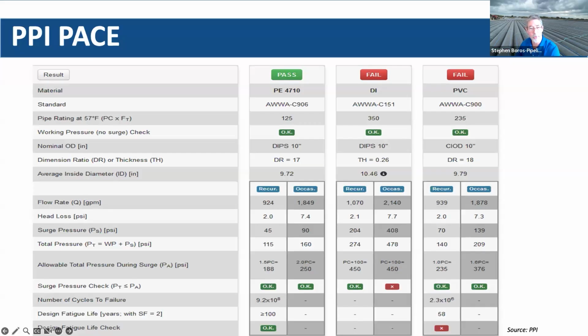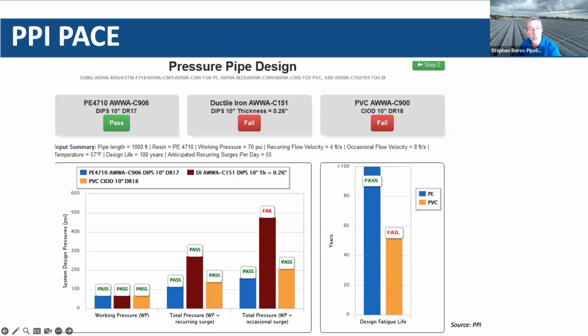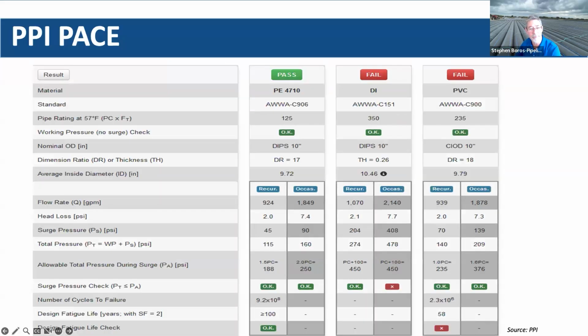Surge pressures, that's where it's going to be different. Polyethylene, you don't have to worry about surge pressures as much because it has a lower modulus. So that resulting energy change, that energy has to go somewhere. In a rigid material, it goes into the pipe wall and results in a high pressure spike. In polyethylene, because it's more flexible, it absorbs that energy, and the resultant pressure spike is much less, half or even a third as much. So it gives you the total surge as well as the working pressure rating to see if that all matches. But here's the real key, and you have to design for this because that's how it's going to fail. What is the fatigue requirement for the material? All materials have them. How many cycles to failure can they handle?